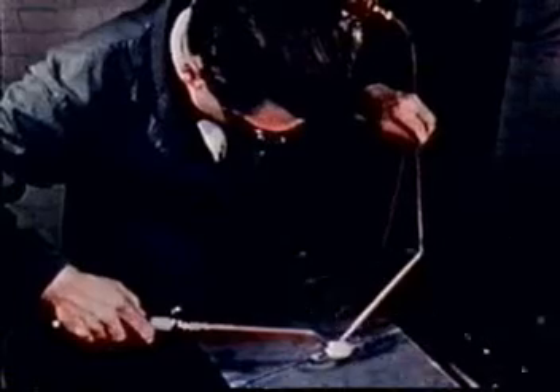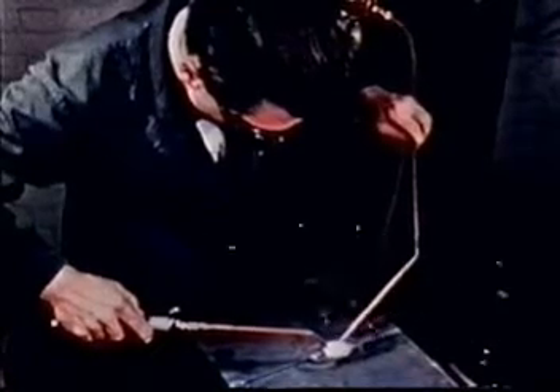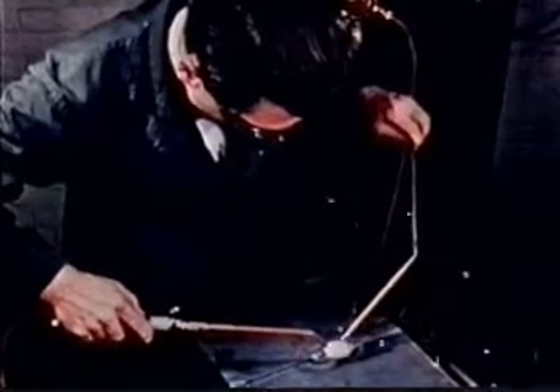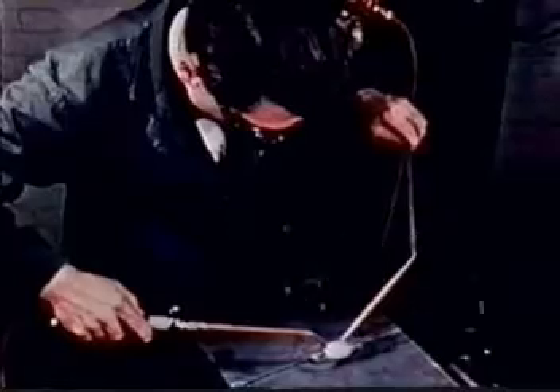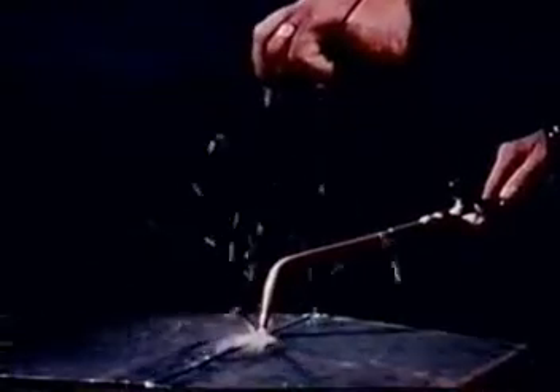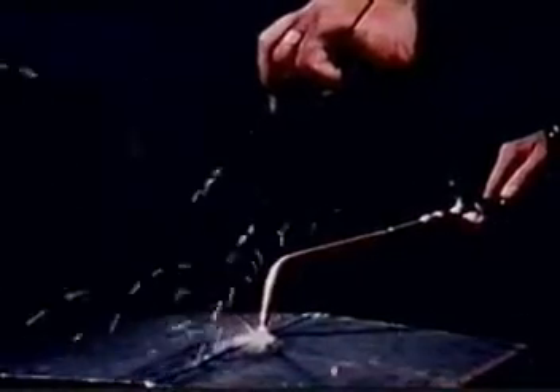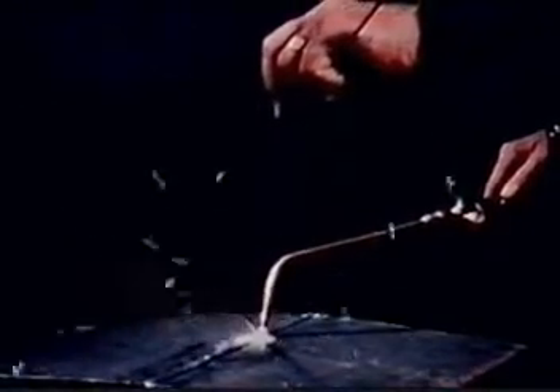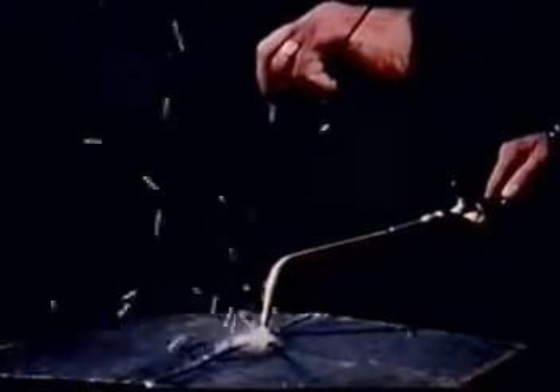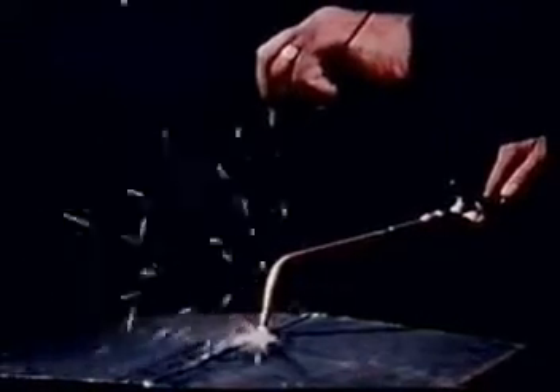When welding, the operator must be relaxed with both arms in a comfortable position. The filler rod should be bent to protect the hand from heat and held at an angle of 30 to 40 degrees, and together they must travel along the line of weld. Whereas in leftward, the flame only melts the metal, in rightward, it melts and supports the weld pool with the filler rod providing the necessary additional metal.